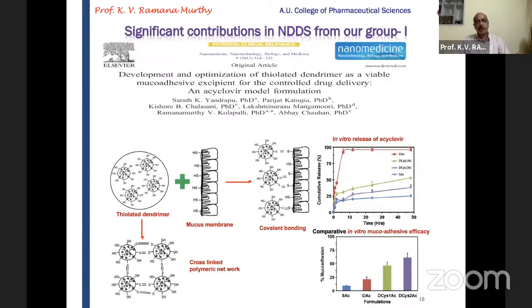This is the first work we attempted for nano formulations, where we prepared second generation, third generation, and fourth generation dendrimers, and they were thiolated with sulfur groups. We tried to evaluate the mucoadhesion properties of these thiolated dendrimers by using acyclovir as a model drug. We proved that the drug release is extended for almost 50 hours, and it has very good mucoadhesion compared to the pure drug or dendrimer-loaded drug molecules.